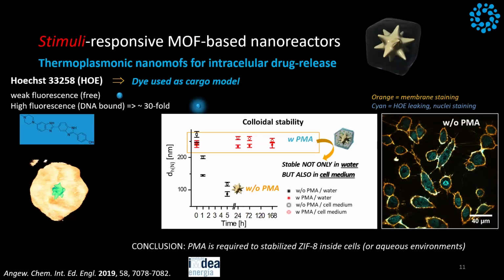So we make a gold nanostar, and then we grow the ZIF-8 on top of it. This beautiful image is a courtesy of Sarah Valls in Antwerp. So you have a gold nanostar, and then you see the structure of the ZIF-8. In this first study, what we wanted to try is if we were going to be able to do what I showed you with the microcapsule, so to put a light pointer on the system.